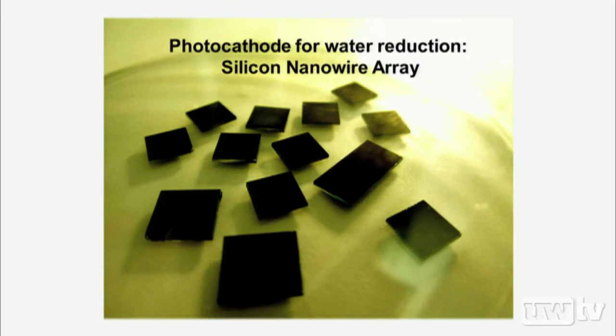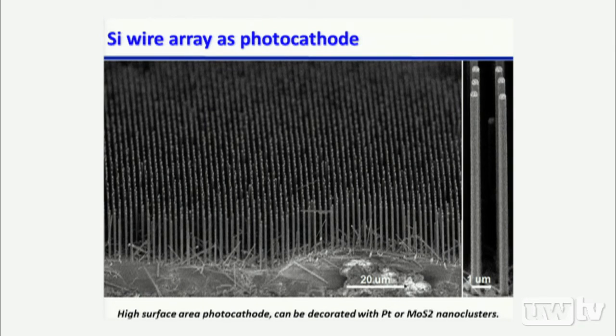So I'm going to give you a couple of examples on the photocathode and also our recent efforts on the photoanode. On the photocathode end, we have a couple of good materials. One is the silicon nanowire array, which looks like very black silicon. These are all highly oriented nanowire arrays. They are black because they have this sort of light trapping phenomenon inside. They have very high surface area. You can decorate them with water reduction catalysts, for example, platinum or molybdenum sulfide in these cases, and utilize them as photocathode for water reduction.